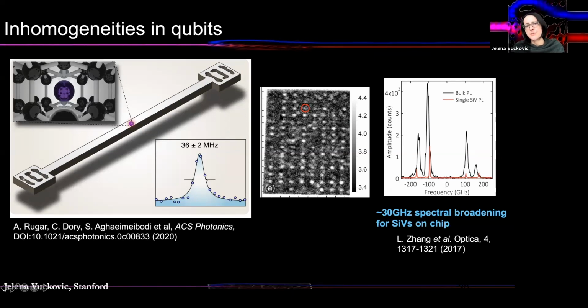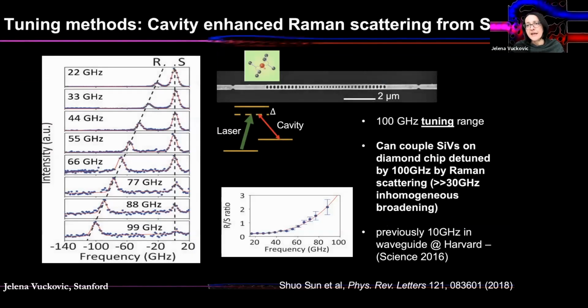And then also, you know, despite our methods for position growth, there are always some inhomogeneities. In spatial inhomogeneities, we can never have really perfect yield of one quantum emitter at the desired position with these methods. And that's why we spent a lot of time handling inhomogeneities. Apart from improving materials, we also developed methods for tuning these quantum emitters onto each other. For diamond, we use Raman scattering. We drive each quantum emitter with a laser beam, which is detuned from the excited state transition. And then by changing that detuning, we can change the frequency of the scattered photon. Of course, something that people have been using in atomic physics for a really long time.